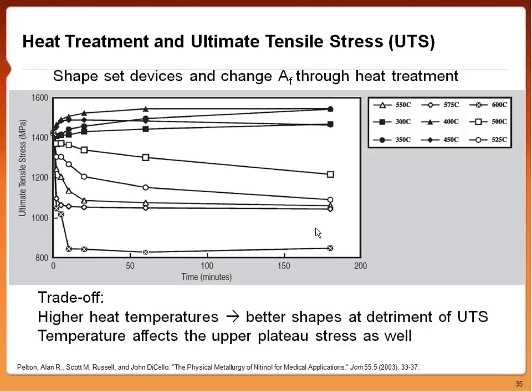And you can also think of the ultimate tensile strength going in parallel with your upper plateau stress, meaning that if you're decreasing your ultimate tensile strength, you're also going to decrease your upper plateau stress and decrease the performance of your device. So really picking your heat treat time to move those nickel-rich precipitates in and out of your matrix to control the properties you want is a trade-off. You really got to pick a time and temperature that's not going to detriment this too much. So these are things you got to keep in mind when you process your material.